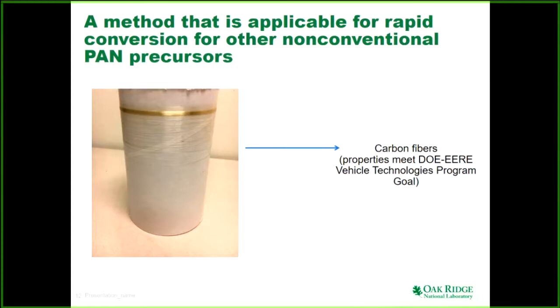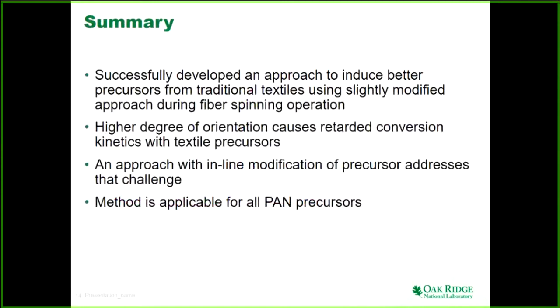And then another component is optional. If it can get converted to carbon fiber without any problem, that is good. But if not, because of a very high degree of orientation, that's what we have experienced, that high degree of orientation retards the oxidation kinetics. So we have devised an option for that. With that, I'd like to summarize that we have successfully demonstrated and developed an approach to induce a better precursor from traditional textiles, and it can be any other precursor too, not necessarily textile-based PAN, using a slightly modified approach during fiber spinning operation. So this modified approach is again the composition and the modifier that we have synthesized in our lab.